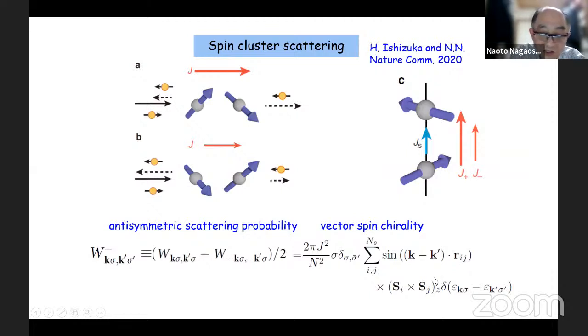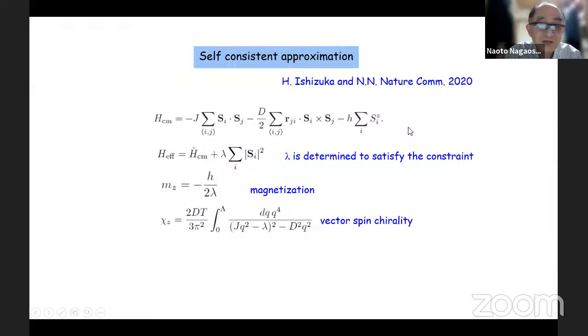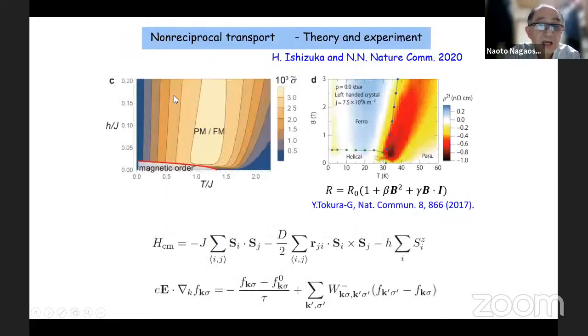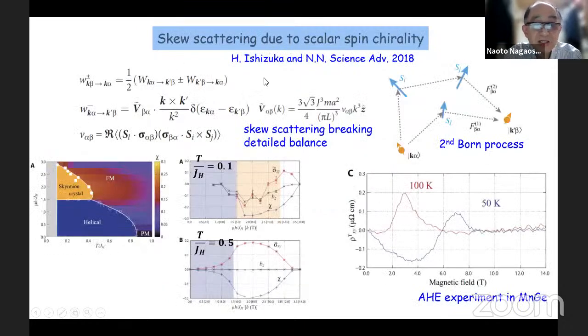And then the next job is to calculate the vector spin chirality together with spin polarization sigma. For that, we take the simplest approximation, namely a mode-mode coupling approximation, and under the magnetic field and finite temperature, we have this peak structure of non-reciprocal transport in this phase diagram, which is quite similar to the experimental observations. So the message here is that vector spin chirality leads to fluctuation of vector spin chirality and then the non-reciprocal transport. So this is a sort of two-spin correlation, but the three-spin correlation is the original Berry flux or gauge flux.